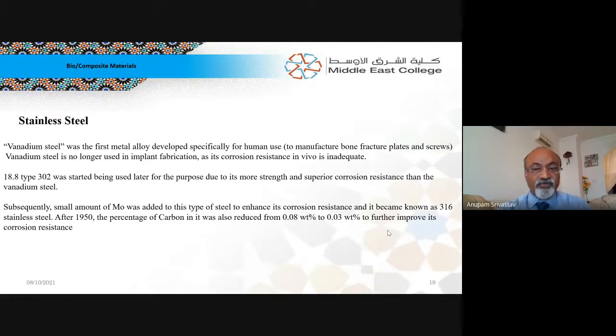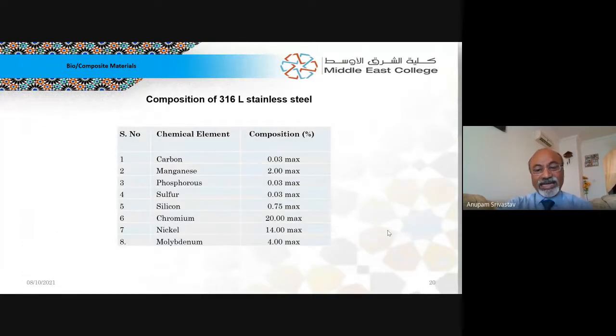Still, it needed further improvement in properties, and therefore 316L stainless steel was finally developed, which had some more alloying elements. Now, what is currently in use in the market since the 1960s is 316L stainless steel, which has carbon percentage only up to 0.03%. Manganese is 2%. Phosphorus is again similar to carbon, and so on. If you see, the highest is chromium, and the next is nickel. So nickel and chromium are the dominant alloying elements, whereas molybdenum and manganese are minor alloying elements, and the rest are trace alloying elements.